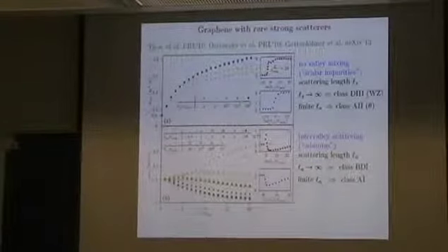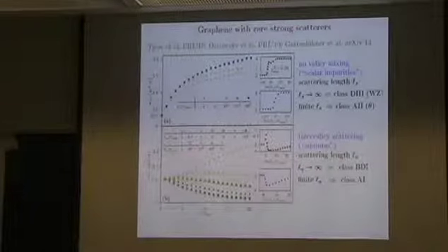First, it's not directly a tight binding model that's modeled. However, it's first reduced so that the scattering on each scatterer is calculated with a T-matrix. This is done analytically, and then you map the problem on an effective Hamiltonian of a size equal to the number of scatterers.